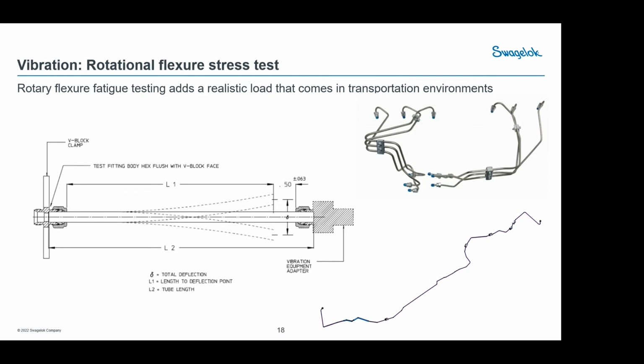Where certain fittings are bite style fittings that dive in and leave a stress riser inside the fitting body, those can crack under this test. Also, ones where the nuts come into contact heavily can crack. This can cause issues with things like O-ring face seals, where that face that was supposed to be locked in parallel starts rocking on itself. So this test really shows what's going to happen when a fitting is in a system where other forces are at play. This is a 10 million cycle test, and it's an important way to be able to look at how fittings are performing.